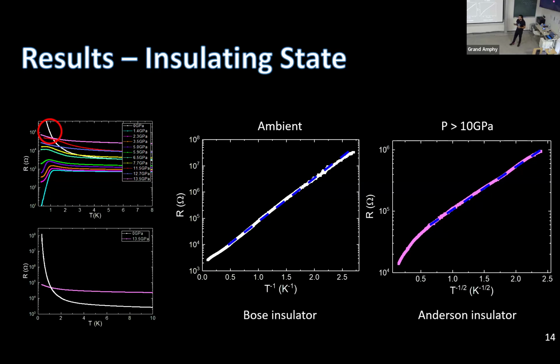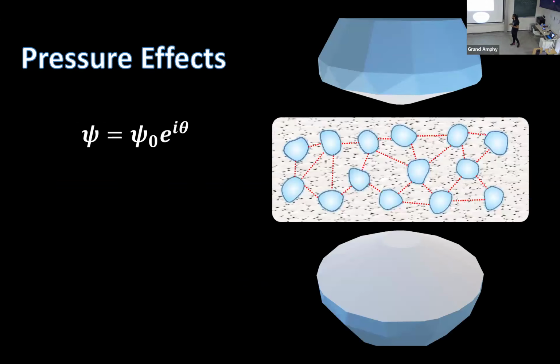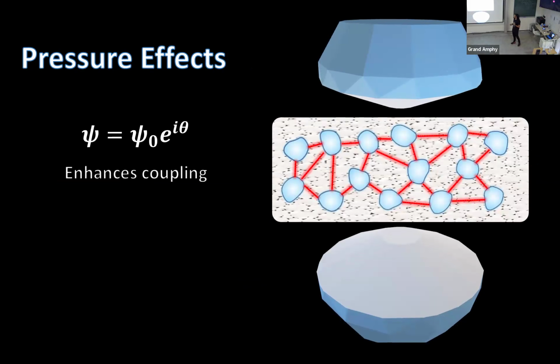So we try to understand what the pressure is doing to our systems. So we took the model of the granular model. We have those indium oxide samples with different grains of superconductivity. Within each of them, we have a superconducting wave function. And when we first apply pressure to our system, we enhance the coupling, we enhance the connection between those two different grains, and thus increase superconductivity.